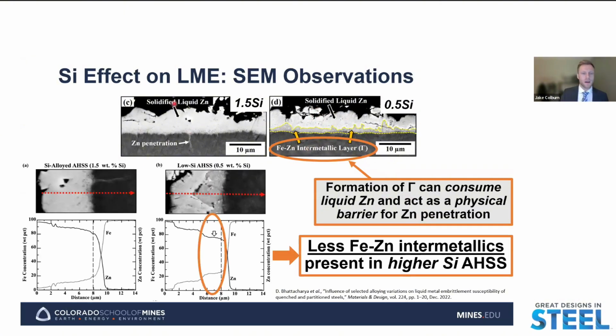whereas with the high silicon containing steel, we don't see the presence of that intermetallic layer, and we're readily able to get zinc penetration into the substrate because there's no inhibition of the zinc into the substrate.